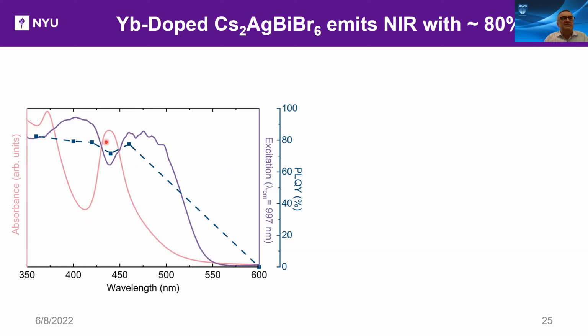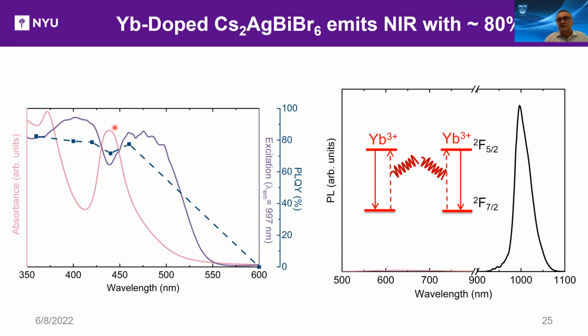And you see there's an exciton peak here. And when we excite with anything under here, come in with, for example, 360 nanometers, etc., we get the material to emit where exactly it's supposed to emit. It's about 1,000 nanometers, corresponding to about 1.25 electron volts, and it corresponds to the ytterbium transition. So basically, this blue light ends up converting to the near infrared.